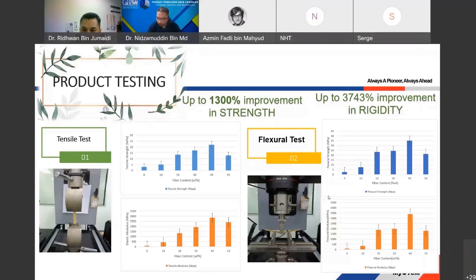So these materials show very high improvement in tensile strength and also in flexural strength. The flexural strength shows up to 55 megapascals. So the strength is almost similar to conventional plastics, for example PP. The strength is almost comparable. This is a very interesting finding that we found when we are using durian fiber.